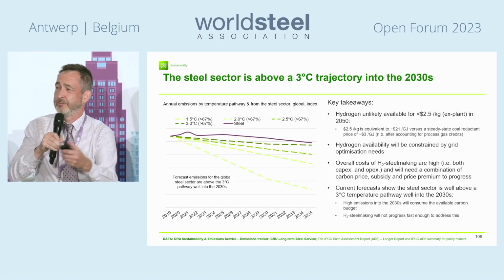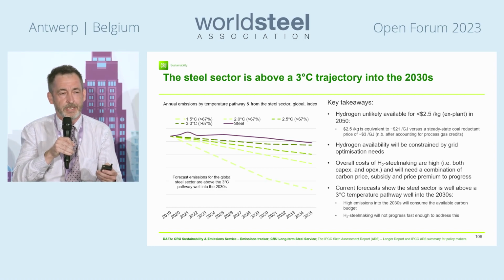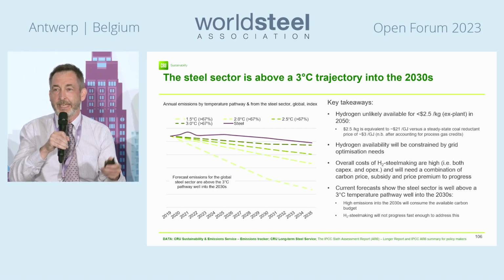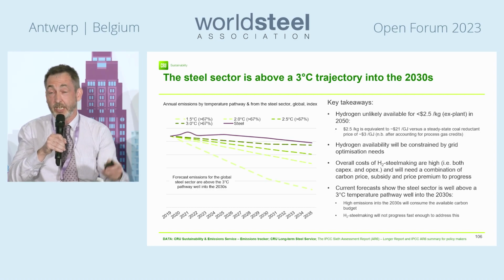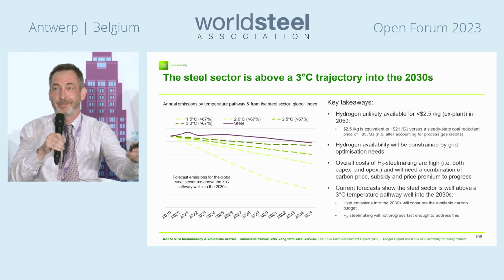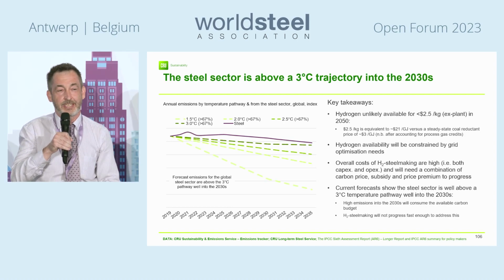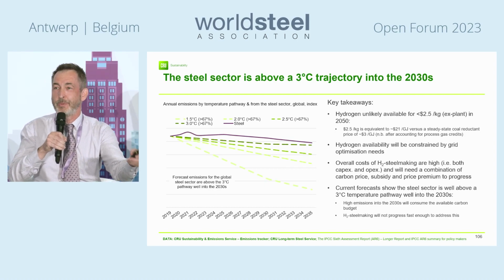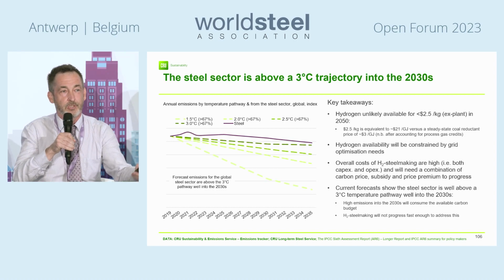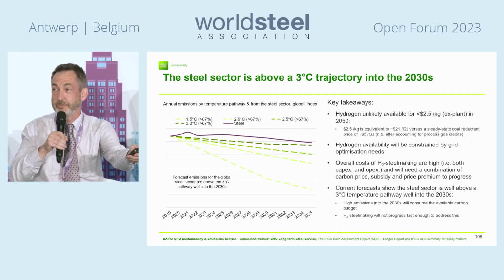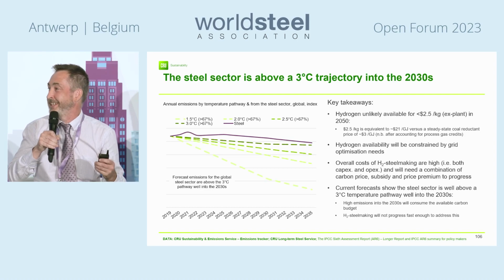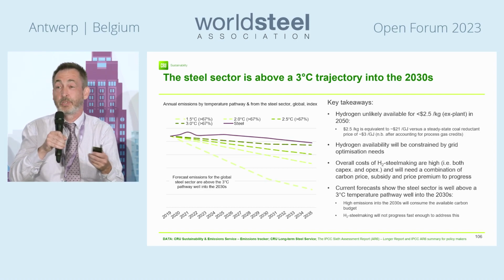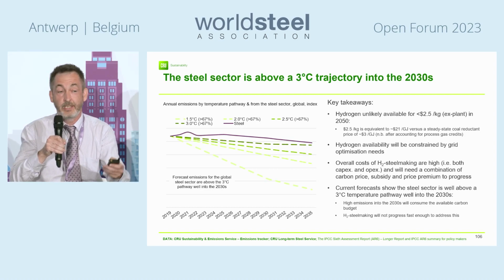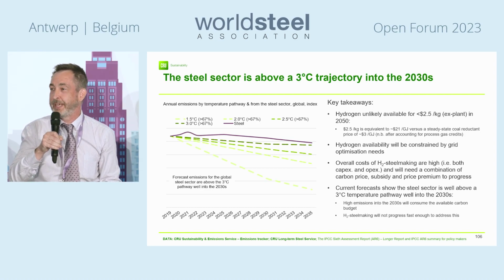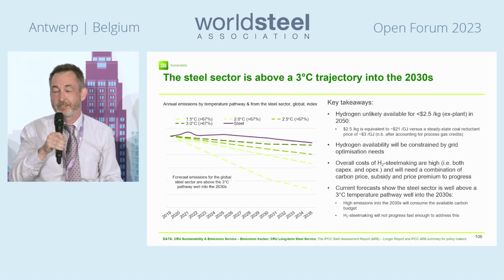Now, what I would argue, and it sort of goes back to some of the things that have already been said, hydrogen-based steel making, H2 DRI with an arc furnace, is hardly going to impact on that emissions because we're not going to build out sufficient capacity in the time to have a significant impact. Scrap is not going to impact on that because we've already taken into account the additional scrap that's available. Those are not solutions for that, and that's eating up the carbon budget incredibly quickly. And in fact, we would argue that the carbon budget for a 1.5 degree under that profile is going to be gone before the end of this decade. So 1.5 degrees is not going to happen, almost certainly. 2 degrees is at risk.